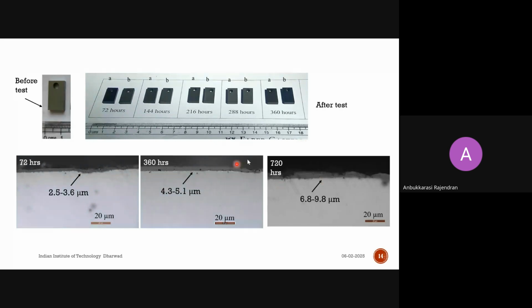So the message from this image is, yes, the optical microscope can be used to reveal the coating also, and you can measure the size of the coating. This image was taken in the as-polished condition. It may not require any etching process, as the coating material is different from the base metal. The contrast difference can help to reveal the coating clearly.